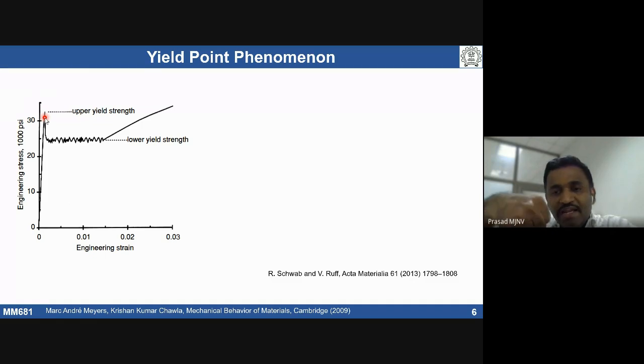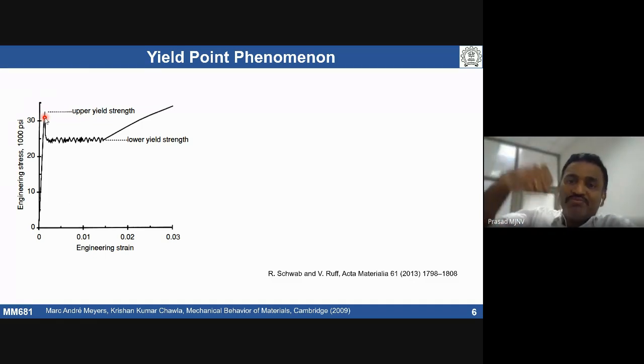When you apply a certain rate of deformation, that means dislocations try to move. When the dislocation is moving, at a certain amount of stress, the dislocation can get unpinned. This unpinning, this unlocking, we are talking about dislocations locked in initially. So after a certain amount of stress is reached, you are unlocking the dislocations. Once you unlock the dislocation from solute atoms, dislocations move freely. That means the stress required for unlocking is higher than the stress required for moving the dislocations. So that is one of the reasons for the drop in the stress.